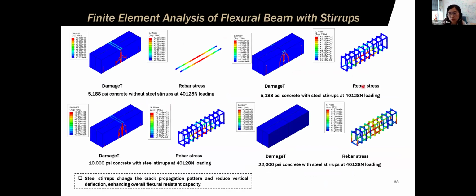And in year 2, we aim to optimize the reinforced concrete design by searching a larger database. So we are expanding our material space by considering more factors like the rebar material. We use the steel rebar in addition to the composite rebar, and also we consider the steel stirrup inside the concrete beam and do more FEA simulations here. And you can see from the simulation result, the steel stirrups change the crack propagation patterns, reduce the vertical deflection, and enhance the overall fracture resistant capacities.